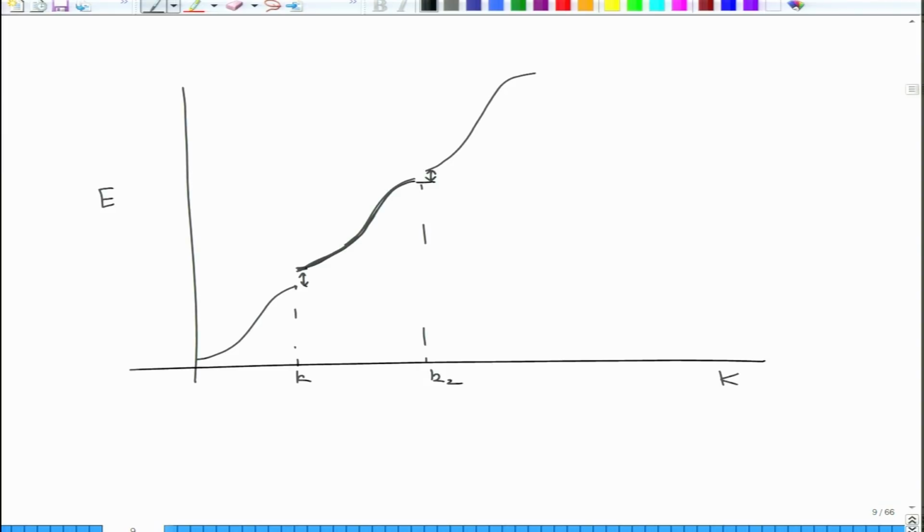So the systems where you have these discontinuities in the energy states in the K space, which are large enough so that they cannot be crossed over by electrons, are generally semiconducting or insulating in nature. They will have a forbidden energy gap, whereas the systems in which energy states are continuous are generally called metals.